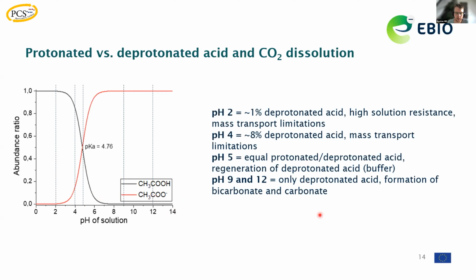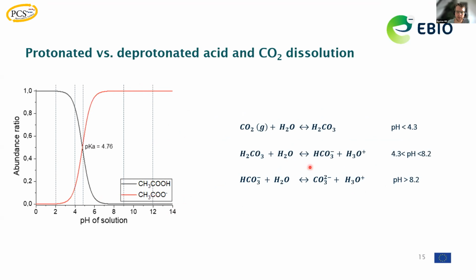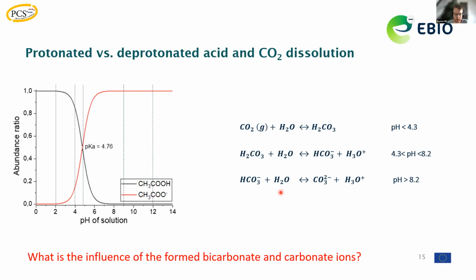And of course, at pH 9 and 12, basically we have fully deprotonated acids, which would indicate that we would have Kolbe processes occurring. But what we also saw is that we couldn't find any CO2 anymore after operating at pH 12. So we checked, of course, the equilibrium between CO2 and carbonate and bicarbonate, and especially at the pHs we operated at, pH 9 and 12, we could see that there are large fractions of carbonate and bicarbonate being formed in the electrolyte.